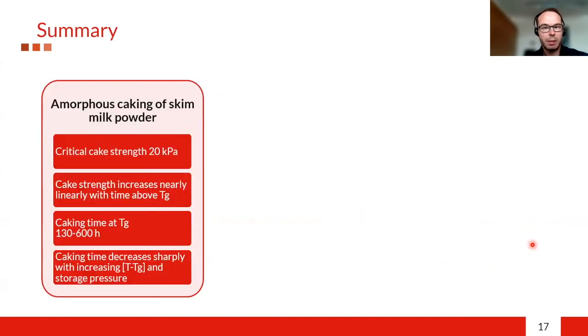So let me summarize the presentation. We have investigated amorphous caking of skim milk powder. We said that we can define a critical cake strength at 20 kilopascal. At this strength, a significant amount of powder was retained by a sieve, so there is mechanical resistance at this cake strength. We saw that the cake strength increased nearly linearly with time above glass transition, and the caking time at glass transition was in the range of 130 to 600 hours. The caking time decreases sharply with increasing temperature difference and storage pressure.